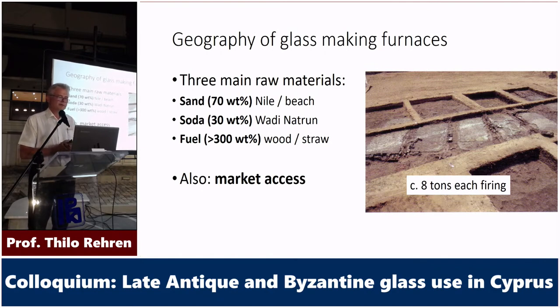Just to briefly point out why people were actually moving the natron, which as a salt is not the easiest to ship, because if it gets wet, it will dissolve, and you are talking seaborne trade here, and not the sand. But if you look at the weight proportions, the soda is only about a third of the weight, while the sand is more than two-thirds of the weight. So it makes much more sense to move the smaller material than the big material. But the real cracker is the fuel.